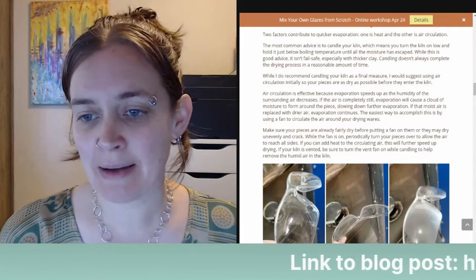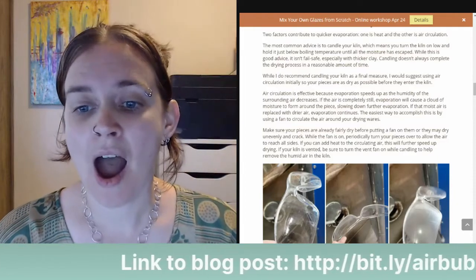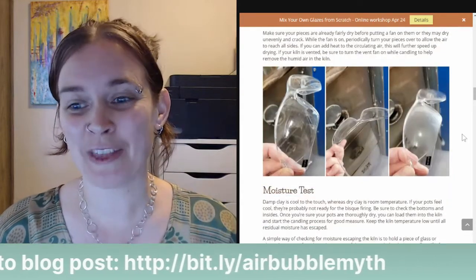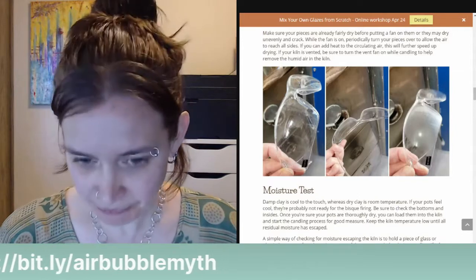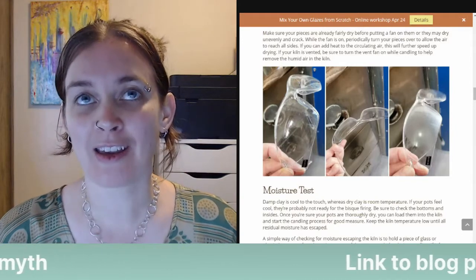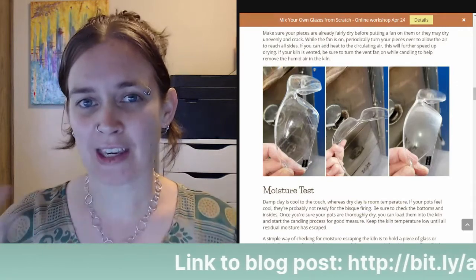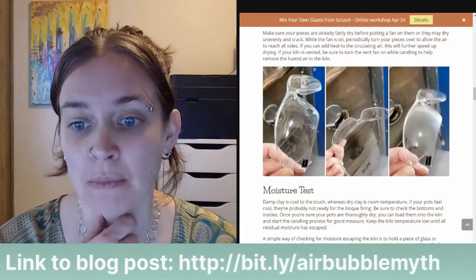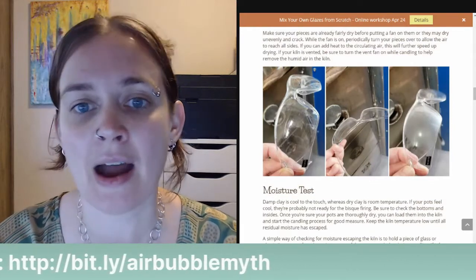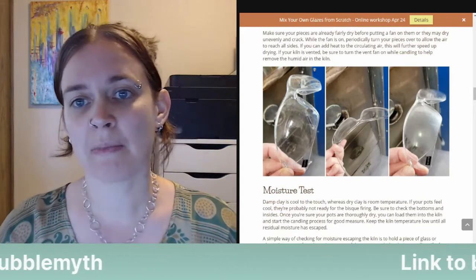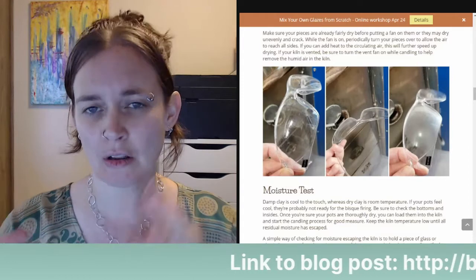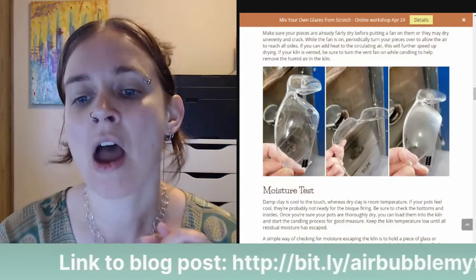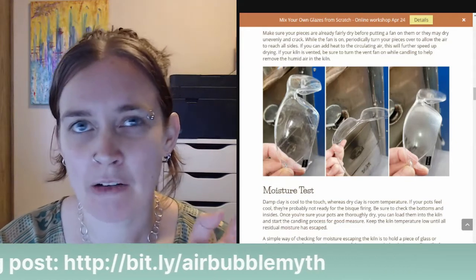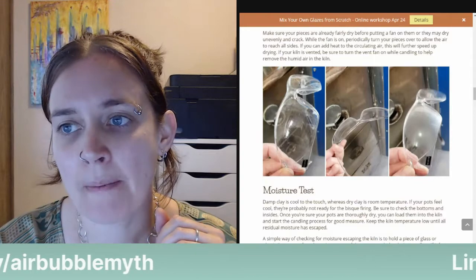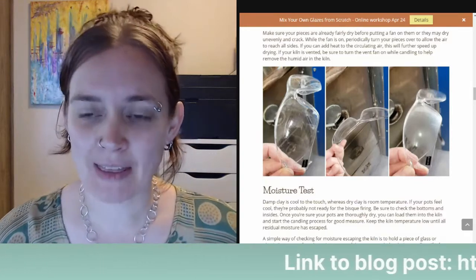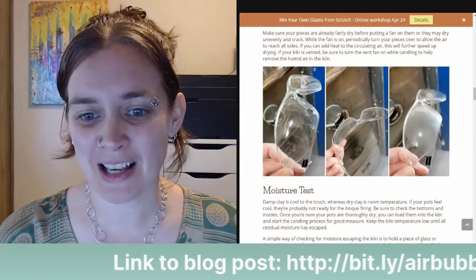And then here is an example of the moisture test that I do when I'm trying to decide if the kiln is ready to increase in temperature. If you've ever fired a kiln full of damp pots before, and you have the kiln preheating, we program a really long preheat on our bisque firings, just because at the rec center we have a lot of beginners, a lot of children working, and so there's a lot of thicker pieces that take longer to dry. So we will hold the temperature of the kiln around 190 degrees Fahrenheit for about 10 hours. And that's just because we want as many successful pieces as possible.